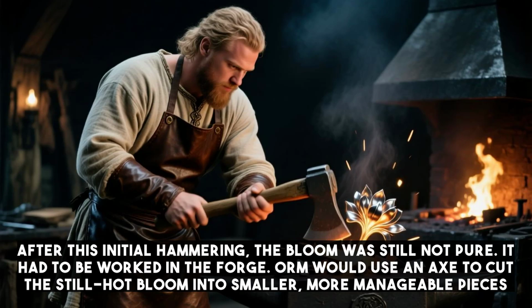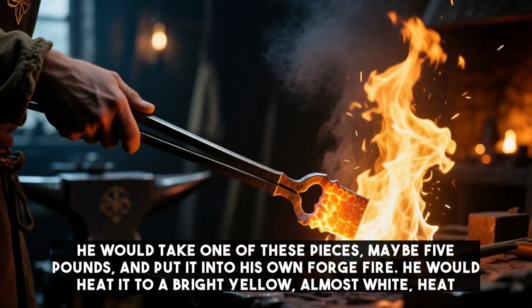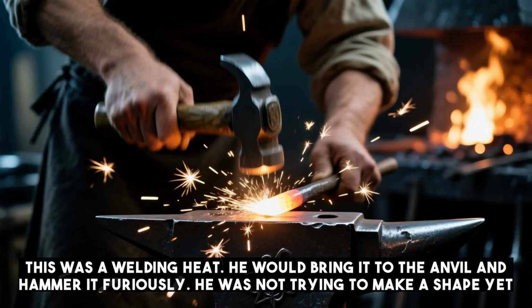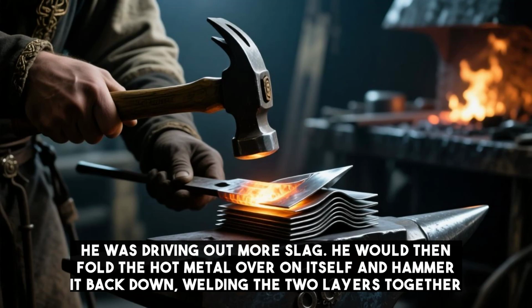After this initial hammering, the bloom was still not pure. It had to be worked in the forge. Orm would use an axe to cut the still hot bloom into smaller, more manageable pieces. He would take one of these pieces, maybe 5 pounds, and put it into his own forge fire. He would heat it to a bright yellow, almost white heat. This was a welding heat. He would bring it to the anvil and hammer it furiously. He was not trying to make a shape yet. He was driving out more slag.